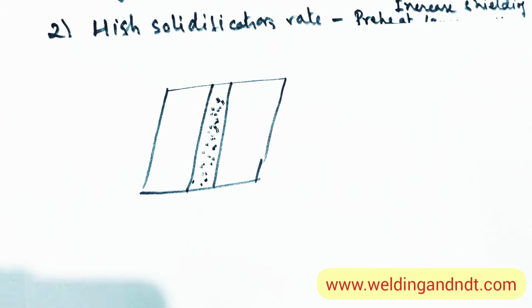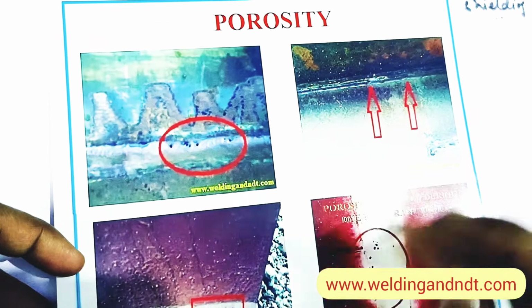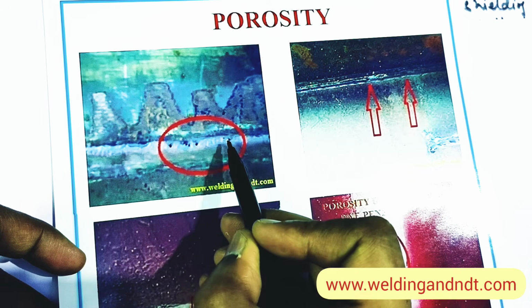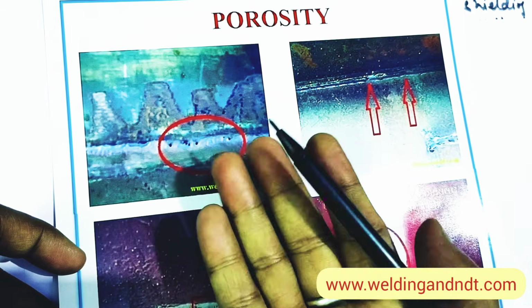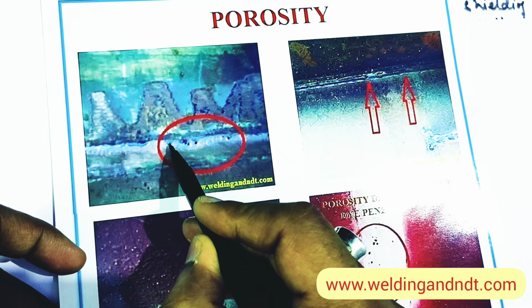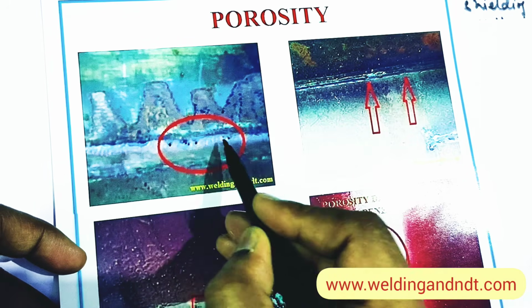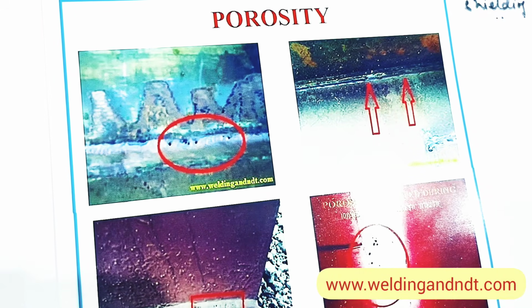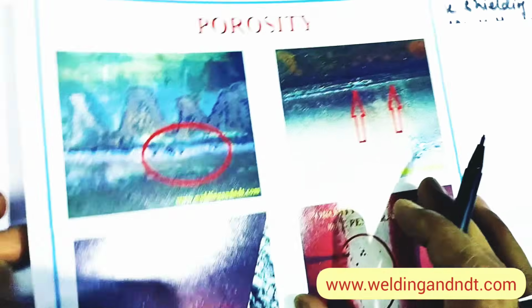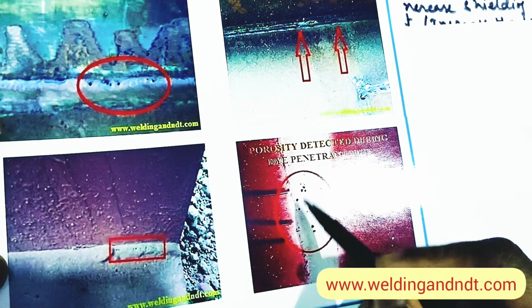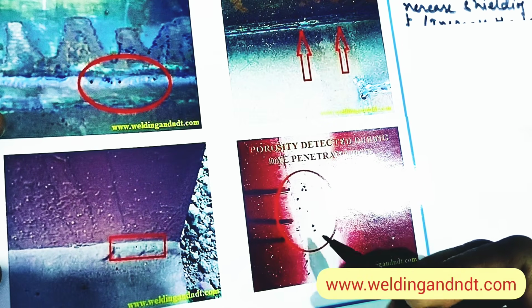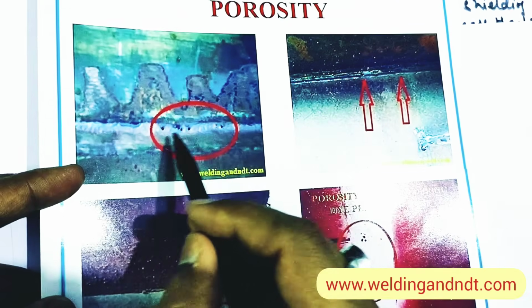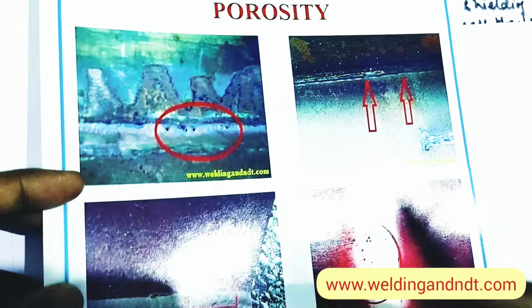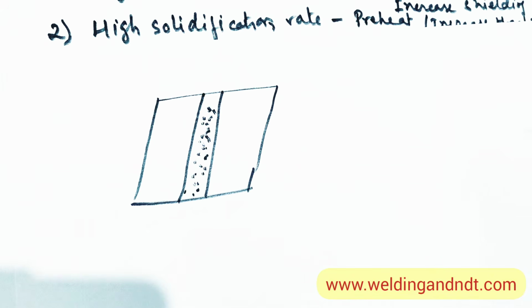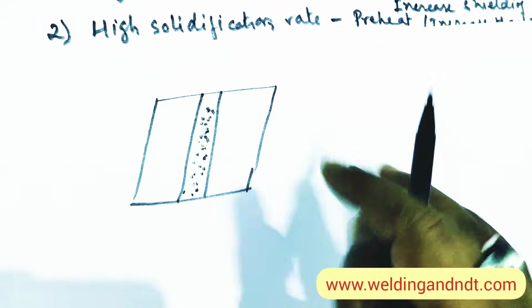Friends, before explaining scattered porosity, let me show you the photograph of porosity. See, here you can see this porosity on the surface, the cavity or the entrapped gases which have come out during solidification. So these are the porosity. Here also you can see the holes, pores, and here these porosities have been revealed or detected after dye penetrant test. So these are the porosities, entrapped gases which have formed porosity. Now this is scattered porosity.